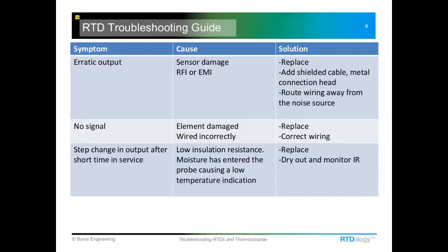Sometimes it might even read okay, and then the temperature will go up. And that's typically an indication that that sensing element has been damaged. So if you can imagine that little coil of platinum wire again, let's say it's been vibrating past what it's capable of surviving, and that wire starts to fracture just a little bit, that's going to start changing the resistance, and it's going to cause that indicated temperature to start jumping around. And as that fracture vibrates, that resistance can change quite a bit, and then eventually it could actually go open